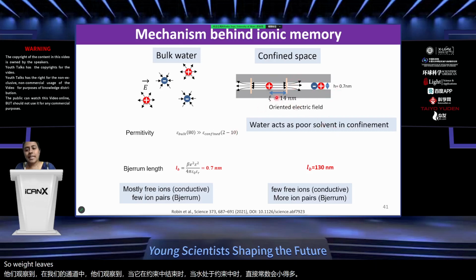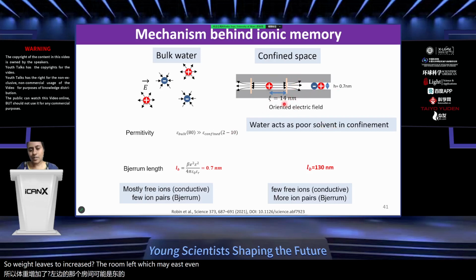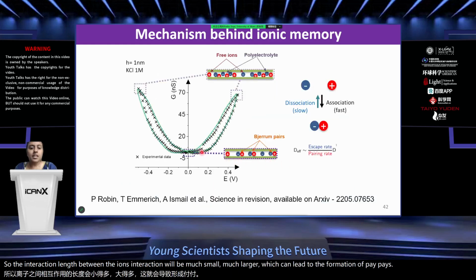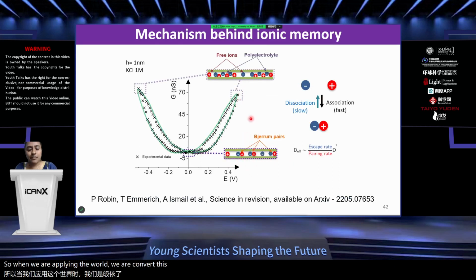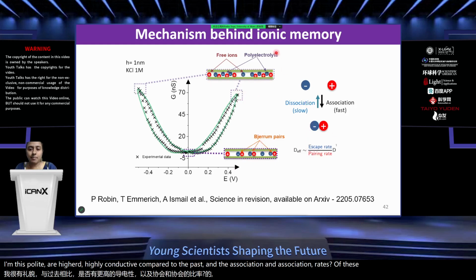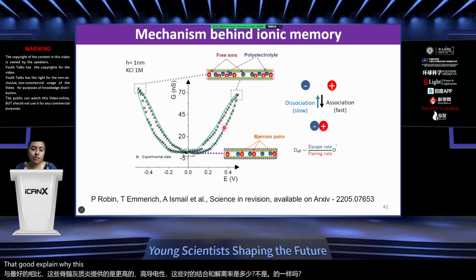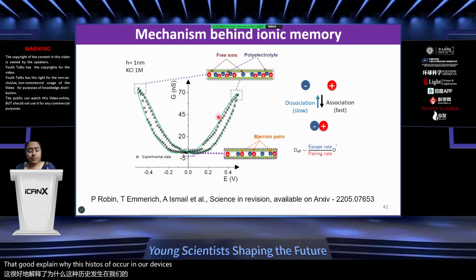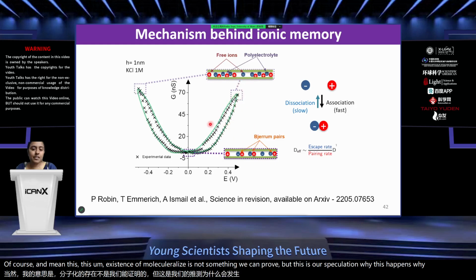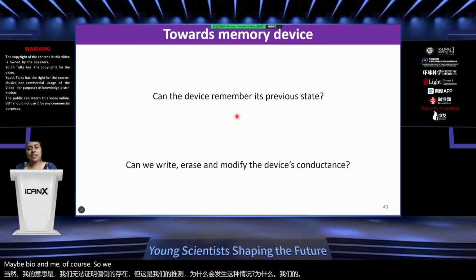Which leads to increased Bjerrum length, which means even though ions are very far apart, they can still interact. So the interaction length between the ions will be much, much larger, which can lead to the formation of pairs. When we are applying the voltage, we are converting these pairs to polyelectrolytes, and these polyelectrolytes are highly conductive compared to the pairs. And the association and dissociation rates of these pairs to polyelectrolytes are not the same. That could explain why this hysteresis occurs in our devices. Of course, this existence of polyelectrolytes is not something we can prove, but this is our speculation of why our memory occurs. With our current understanding, that's what we think.